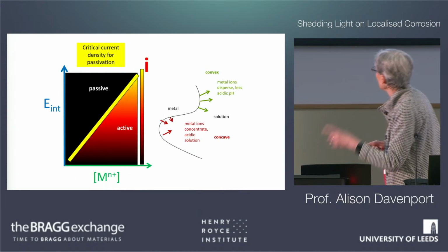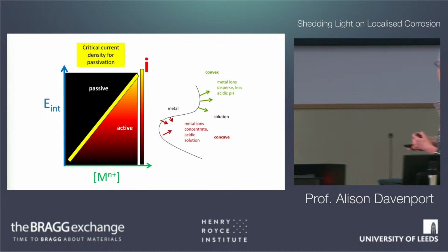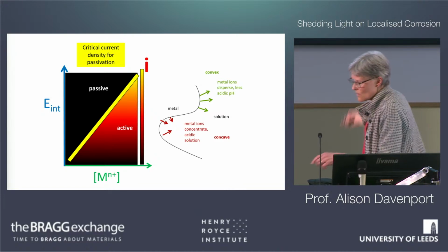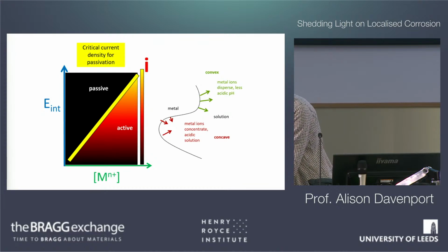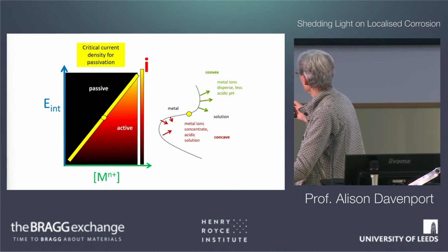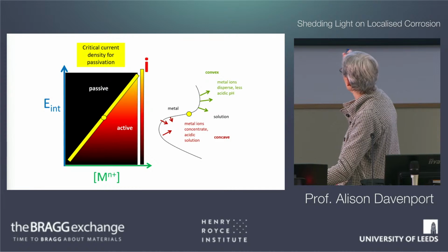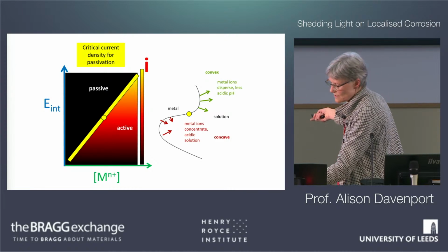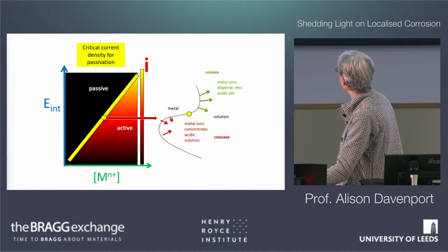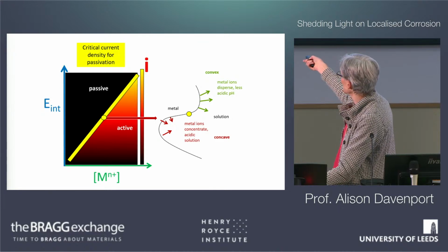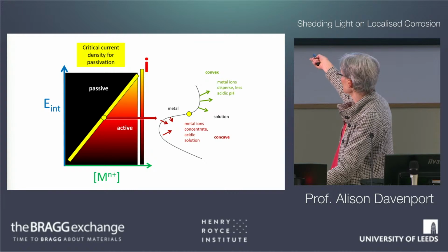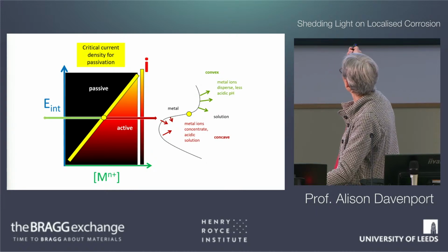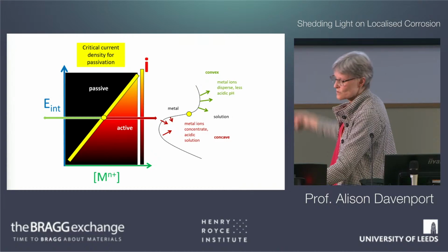And if you think about it in this framework, essentially, this is exaggerated here. What we've got is a tipping point. The tipping point here is where it's pretty linear, and that's represented by this point here on the line. What happens is that if you're in a concave region, it'll take you into a more active direction, so you'll go in this way, and conversely, if it's convex, you'll go in this direction, so you'll go passive.